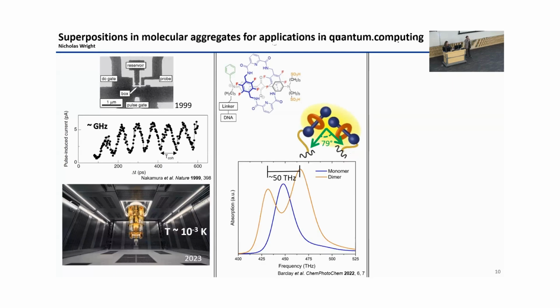This is obvious in the steady state absorption spectra, which you can see in orange, which shows that when packed into a dimer, there's two optical transitions at lower and higher energy than the optical monomer. Theoretical work has shown that if these transitions can be simultaneously excited, there exists a quantum superposition at the terahertz scale frequency, much higher than the gigahertz frequencies of the superconducting quantum computer.